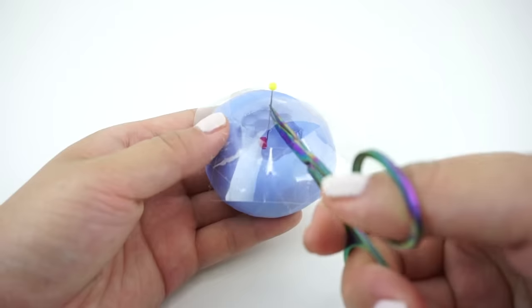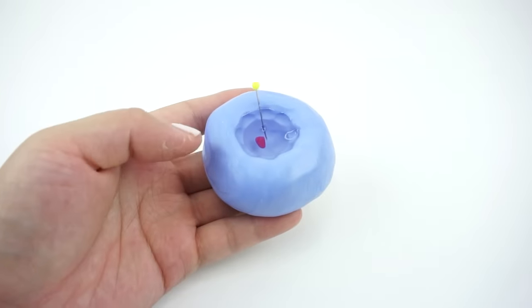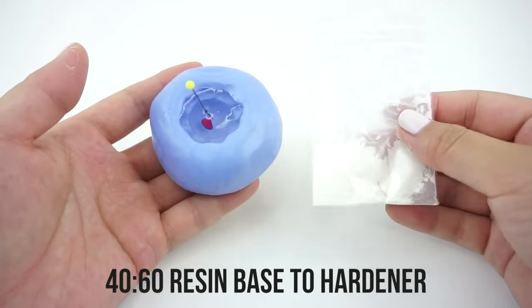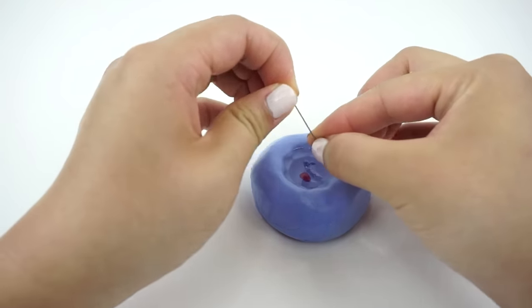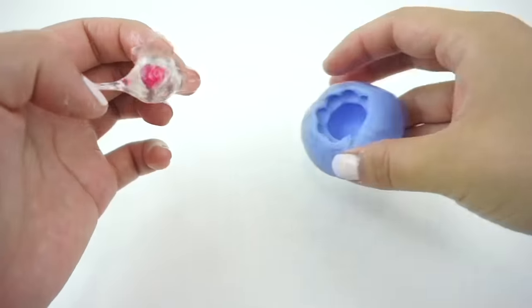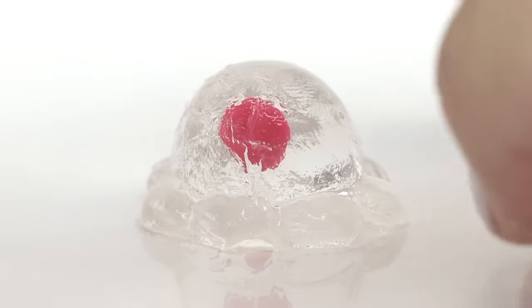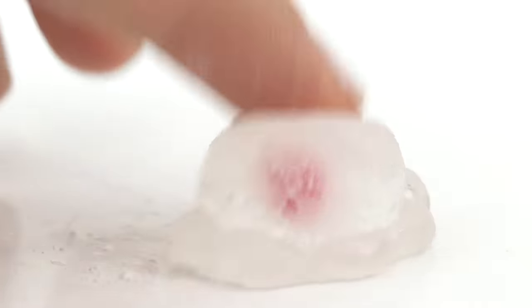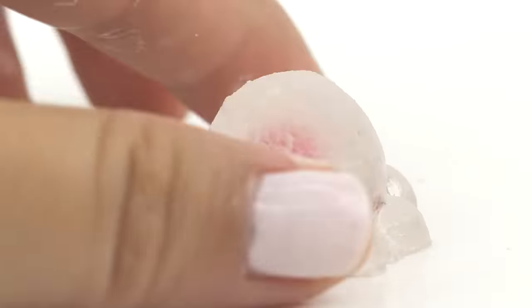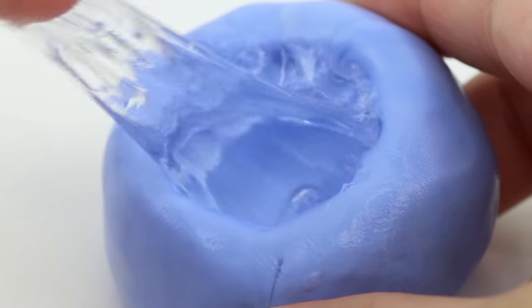So with that mystery solved, let's check back on the Hitohata Gel. This one took almost a week to cure, and it was still a bit too soft, so I would definitely recommend adding a bit more hardener when you're mixing your resin. I think a ratio of 40 to 60 will work much better than 50-50. The method I used with the pin actually worked very well, and I was able to detach it without any problems. But the biggest issue is that the squishy is still too soft. I tried adding the talcum powder that came with the Hitohata Gel to make it less sticky, but this just ended up turning everything cloudy. I still had one more mold with a plain transparent octopus inside, and this one turned out quite cute. I would recommend using slightly more hardener and skipping the talcum powder, so your squishy stays crystal clear.